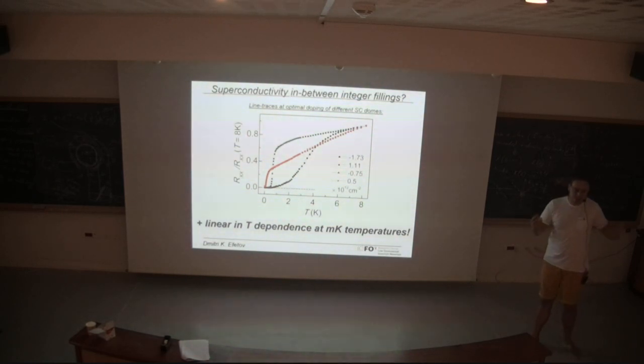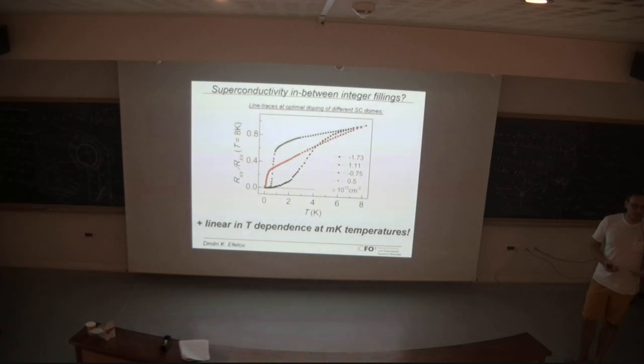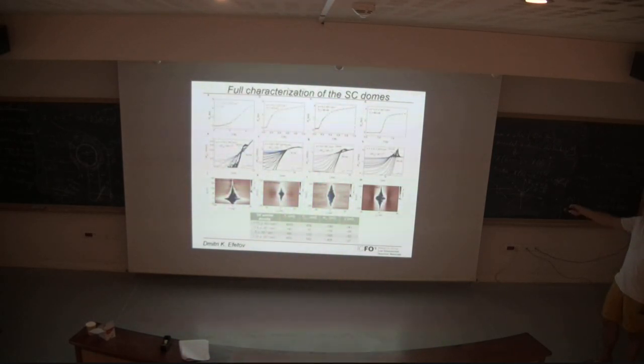So in principle, we observed superconductivity, we haven't actually gotten to analyzing and thinking about it. Maybe these are different types of superconductors, right? So they could be very different, and they could originate from very different ground states. And basically for all of the superconductors, again, we extract TC and BKT transitions. We extract coherence lengths, HC2s, etc. So in principle, from these numbers, one can maybe start to try to compare them. For sure, the BKT transition in the 3 Kelvin superconductor happens at much lower temperatures, and it's much more broadened as we see. And for the other superconductors, it's much sharper as well.